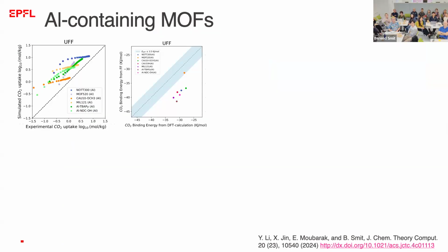First, improving force fields. If you do these screening studies, you use a classical force field to predict the adsorption isotherm, that is, how much CO2 gets adsorbed in these materials. So what you see here is the experimental CO2 uptake and the simulated CO2 uptake. If you had perfect agreement, it would be along this line. What this is showing is that these materials, these different MOFs with aluminium, are performing really very poorly. And if you calculate the binding energy with DFT, you get the signature that the DFT binding energy is really off from the binding energy you would get from your classical force field. This is well known, because this is the universal force field we're using, and it performs very poorly if you have aluminium.